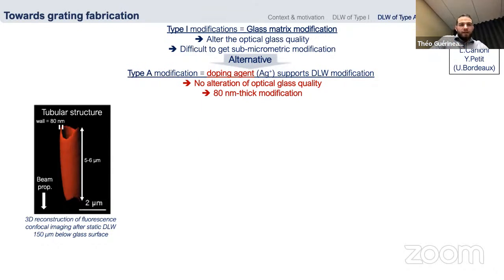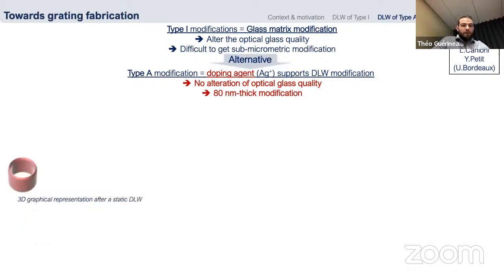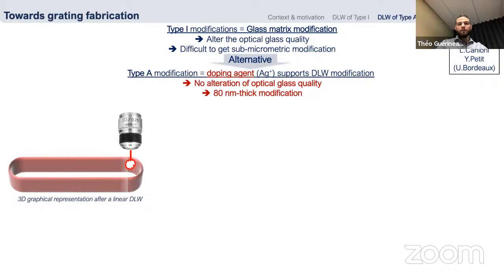You see here a tubular structure after a static irradiation. Even if the height of this structure is about 5-6 micron, the thickness of this structure is about 80 nanometer. Here is just a 3D graphical representation of this static direct laser writing. And during a linear direct laser writing, you see that we can extend this thin wall in some dimensions.